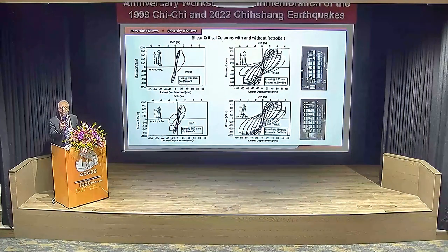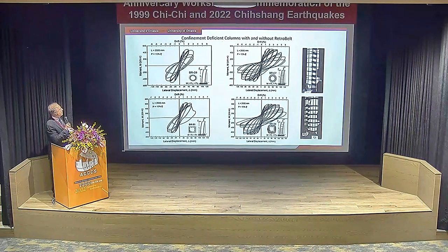Now I'd like to show you very quickly the results. These are shear critical columns. These are bridge columns having 500 millimeter square cross-section specimens in the lab. They're subjected to low levels of axial load, 15% of P0, because they are bridge columns. And on the left-hand side, you see brittle shear failure at about 1% drift. On the right-hand side, application of Retrobelts resulted in improvement up to 4% drift. And you can see similar response in the square column just below.